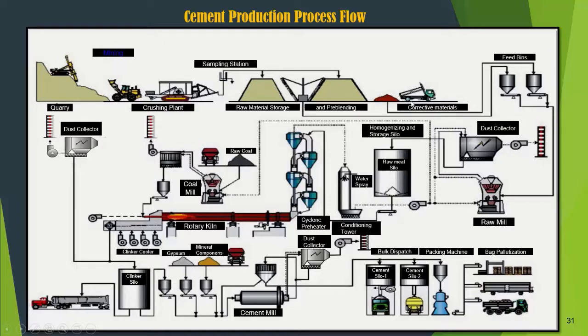The next process is the raw material milling process. Limestone, clay, silica sand, and iron sand are put into the feeding bin, prepared for feeding to the raw mill system. These materials with a predetermined composition are entered simultaneously into the raw material milling process to a certain fineness of 12–14% on 90 micron. Some equipment uses a tube mill and some use a vertical roller mill. This process requires hot gas for drying the material, reducing water content from more than 10% to less than 1%. The hot gas is taken from the remaining combustion gas in the kiln system.